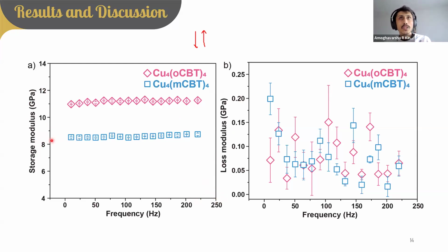To define them, the storage modulus is the amount of energy stored within the crystal when we apply the force, and the loss modulus is the amount of energy lost from the crystal due to acoustic vibrations or thermal vibrations, etc. Now we can see the storage modulus is quite high and is frequency independent in both the samples, and is quite similar to the reduced Young's modulus for copper 4 MCBT and slightly higher in the case of copper 4 OCBT. This indicates that my material is showing frequency independent storage modulus. And in the case of loss modulus, the loss modulus is quite low compared to the storage modulus. And it is showing slight frequency dependency only because the scale is very small when compared to the storage modulus.